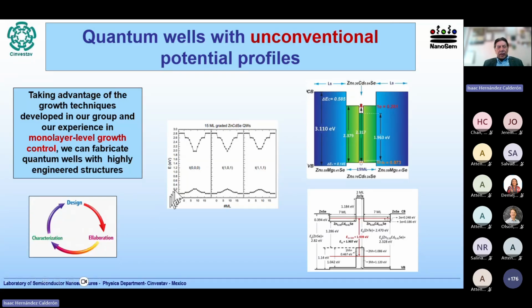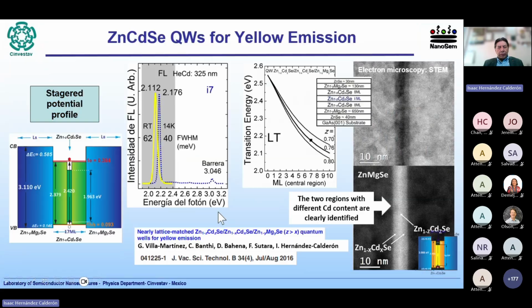That is the growth. Instead of just rectangular quantum wells, we have grown quantum wells with what we call unconventional potential profiles. So I have 3 examples for this. One of them is this type of staggered potential profile. So in a typical quantum well, we would have a rectangular quantum well, but we have the capability of changing the composition of each individual monolayer in real time, during the growth. That's a great advantage. So typically, it's expected that these materials, zinc selenide, will be useful only for blue and green emission. But by making band gap engineering, we can tune the emission to lower energies.